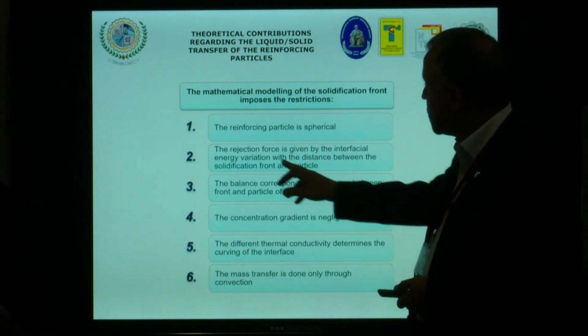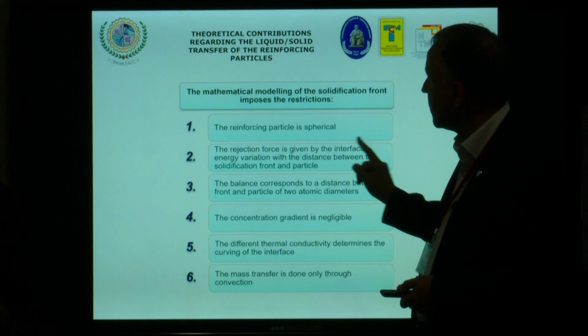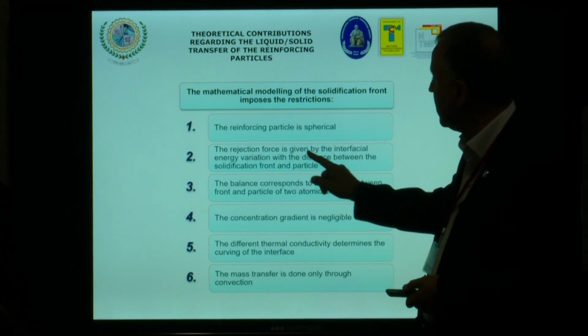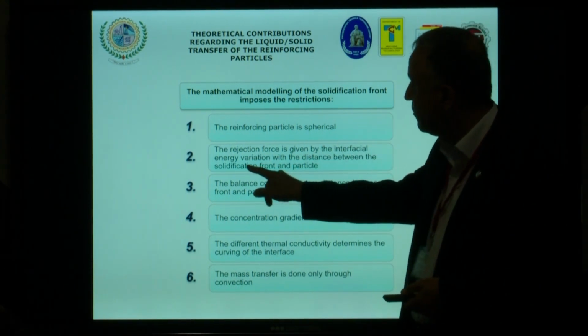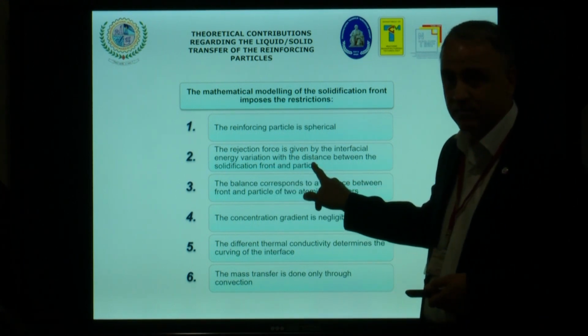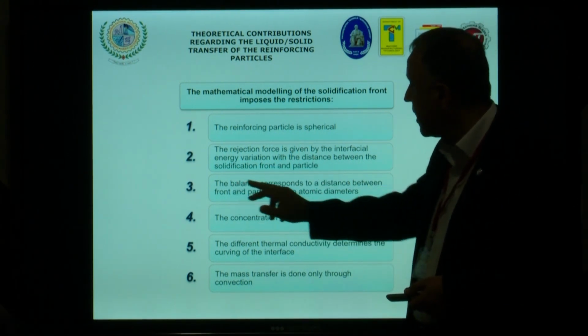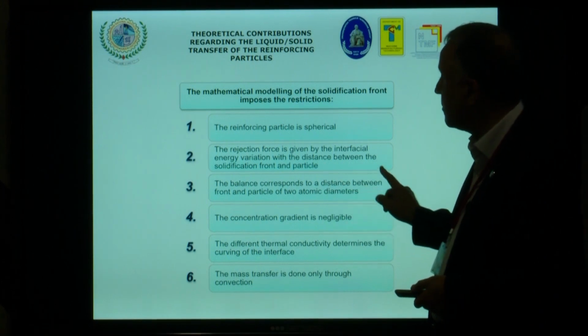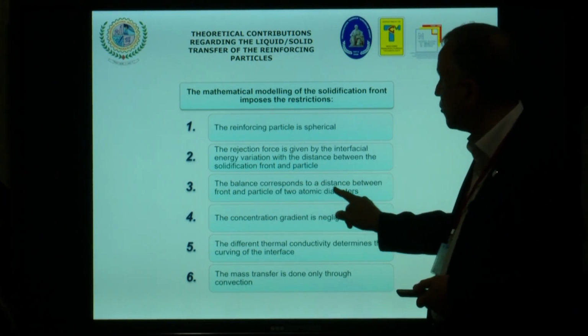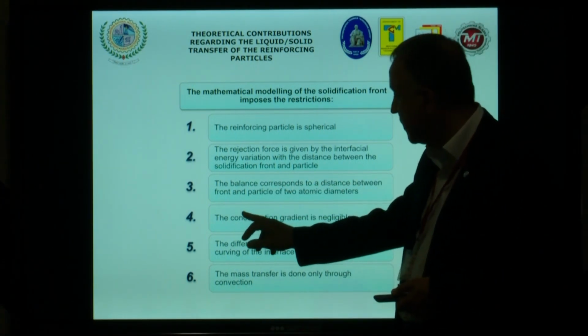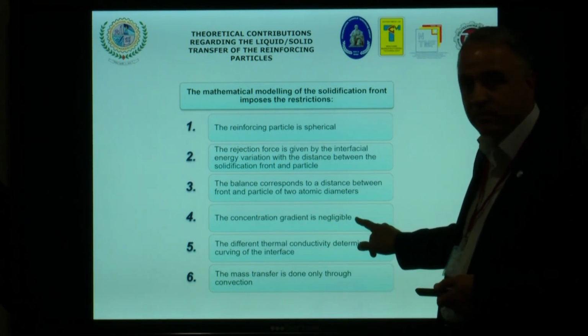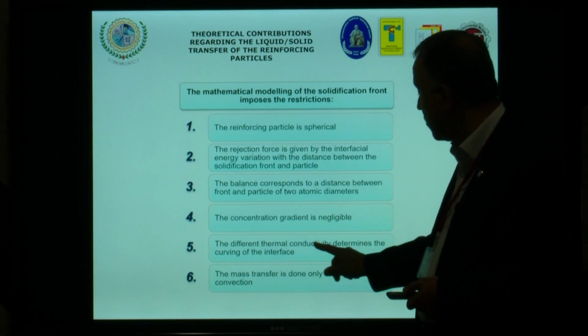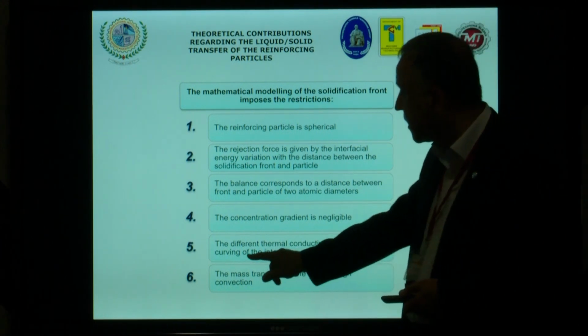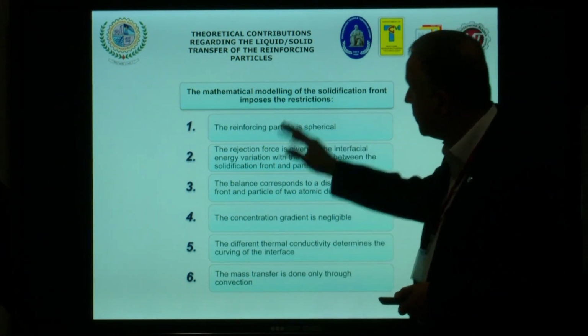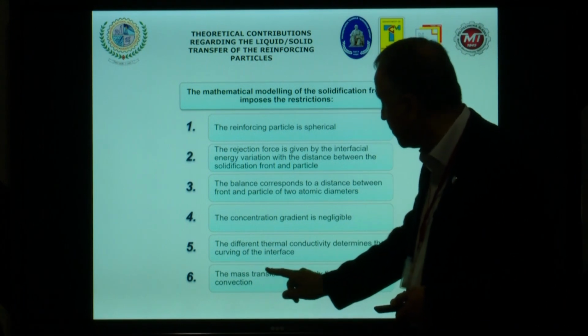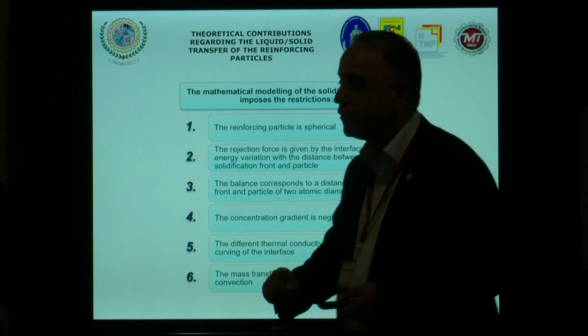The next one, the rejection force is given by the interfacial energy variation with the distance between the solidification front and particle. The third one, the balance corresponds to a distance between front and particle of 2 atomic diameters. The concentration gradient is negligible. The different thermal conductivity determines the curving of the interface. And the last restriction, the mass transfer is done only through convection.